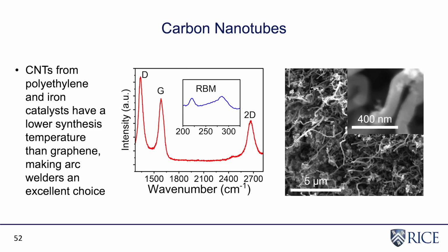And through this, we took that little $125 arc welder plus $50 in electrode supplies, just 2 carbon electrodes, and you can make very nice flash graphene. It's turbostratic, which you can tell by the TS1 and TS2 bands in the Raman spectrum, and you can make very clean flash graphene. And if you add an iron source, some ferrocene, instead of making graphene, you end up making carbon nanotubes. So you get the carbon nanotubes just by adding iron.